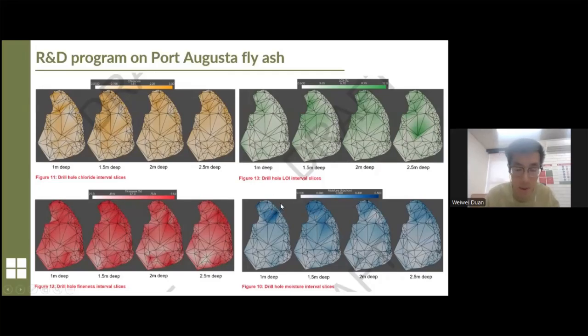Because the chloride is dissolved in the moisture, if we look at the chloride map, we find that the north side has a relatively slightly higher chloride content than this side. And the fineness is more related to the depth of the sample-taking point. This is because the fine material flows easily and the coarse material is likely to settle.